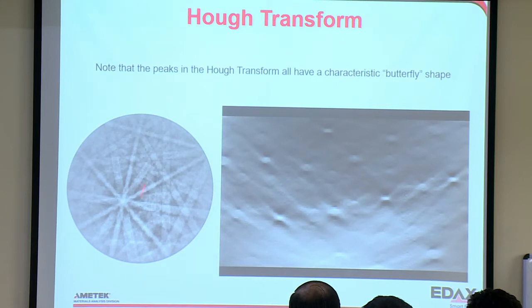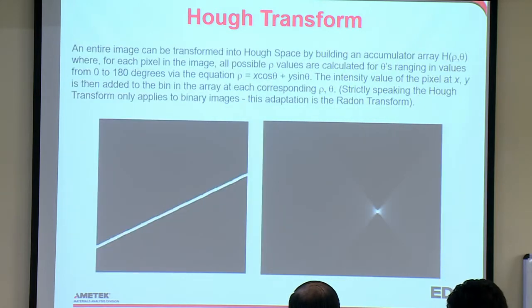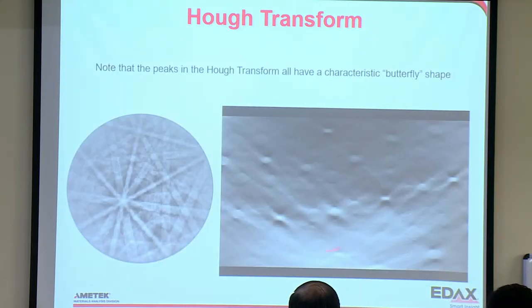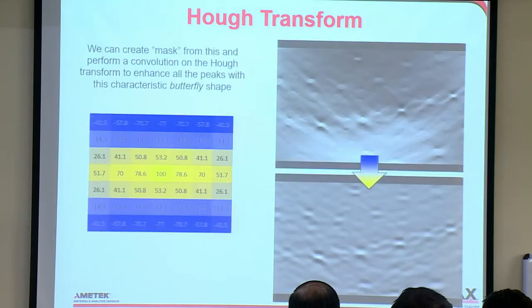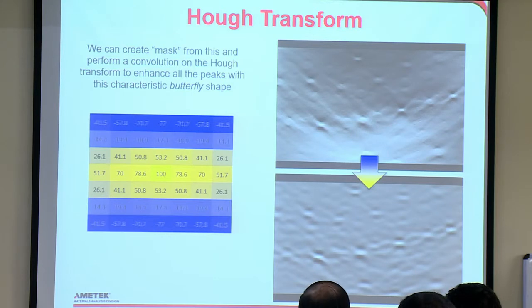So I mentioned this butterfly shape. If we go to this picture now, you can see how these real bands still produce these butterflies. It's really obvious with this one. You can think of the butterfly shape in the intensity like this. We apply a convolution mask to the raw data, and it highlights the ones that have this characteristic butterfly shape. It creates this transform here, and now we really can just look for peaks.